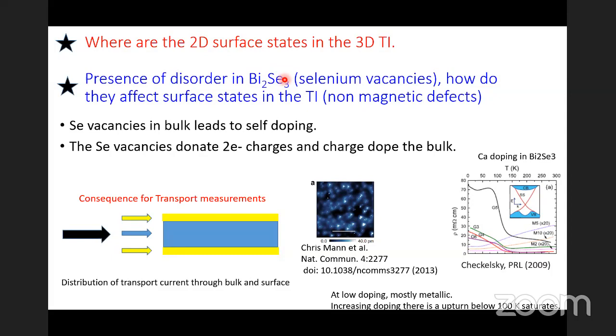And when we look at Bi2Se3 type of samples, there is a very important effect which happens in these materials: there are selenium vacancies. They actually charge dope the bulk. So this is the surface of Bi2Se3, where these triangular defects in STM images show the presence of selenium vacancies. And when selenium vacancies are generated in the bulk of the material, they generate electrical charges in the bulk.